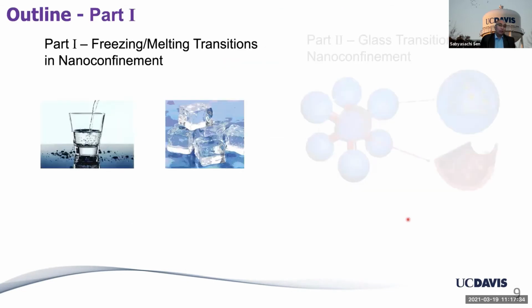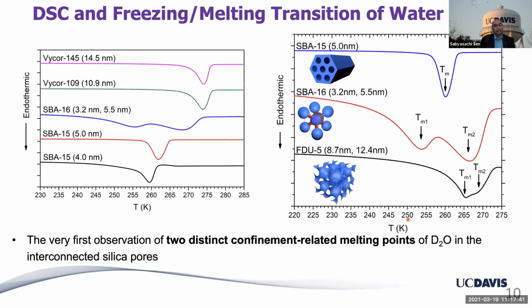And now to the material behavior or liquid behavior in these pores. So first is the freezing-melting transition. Typically you study freezing-melting behavior, and the first thing you do is to run a differential scanning calorimetry scan. So these are heating scans of water. As you can see very clearly from a very quick look, when the pore size is 15 nanometer, the melting point onset is somewhere here, whereas the onset moves to a lower temperature when you go to 4 or 5 nanometer. So clearly size has a very strong effect.